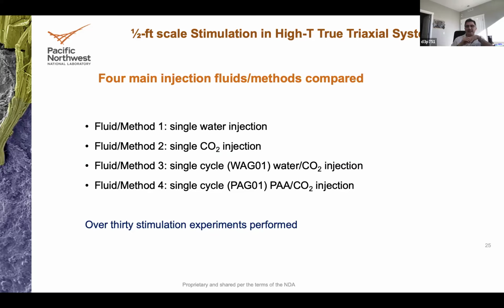What we can say is that both StimuFrac, the polymer, and the CO2 have very low interfacial tension; supercritical CO2 is nearly zero. So I would guess there is miscibility, mixing and transport of one fluid into the other and into the formation due to the very low interfacial tension. But once this fluid gets to temperature and starts reacting, that will happen in an injection wellbore, and into the formation and away from the wellbore when the temperatures are higher.